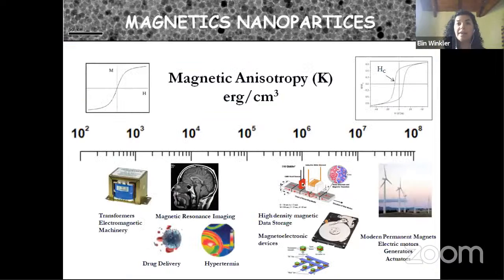Well, the magnetic anisotropy is one of the main characteristics that determine the range of application of particular systems. Here, for example, we are drawing different applications as a function of the magnitude of the magnetic anisotropy constant. If the magnetic anisotropy is very low, we are talking about soft magnetic materials, and that can be used for transformers, and also biomedical applications require material with low anisotropy. When we increase the anisotropy constant, we can design material for high density data storage, or in this range, we are talking about hard magnetic materials that can be used to design a permanent magnet.